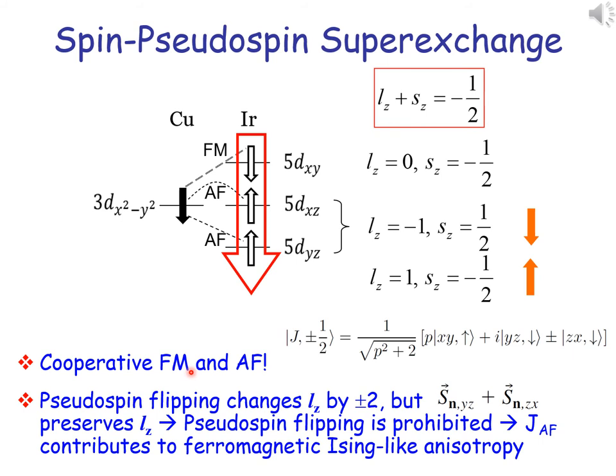Then, what about the large gap in the magnetic excitation spectrum? We notice that the flipping of the pseudo-spin changes the Z component of the orbital angular momentum LZ by ±2. But the internal super-exchange processes involving the XZ and YZ orbitals preserve LZ. Therefore, the flipping of pseudo-spins is prohibited, yielding Ising-like exchange anisotropy. Notably, this ferromagnetic exchange anisotropy comes from the original anti-ferromagnetic super-exchange processes.